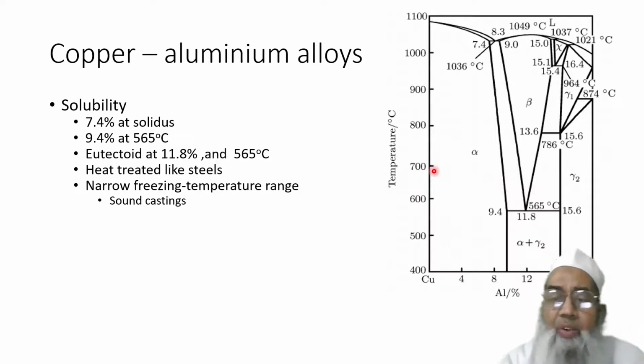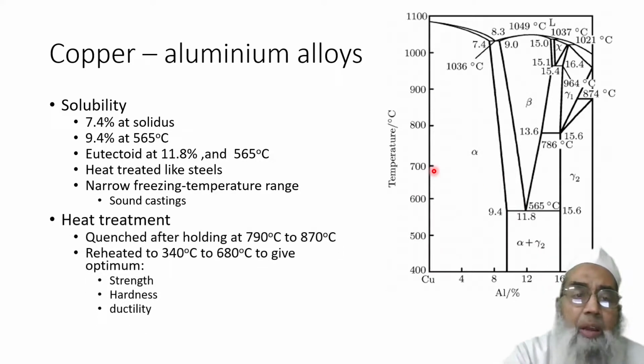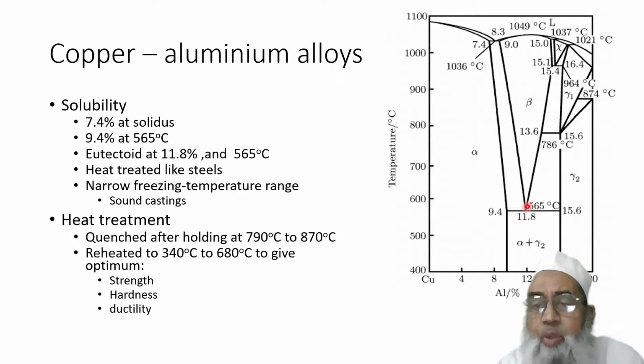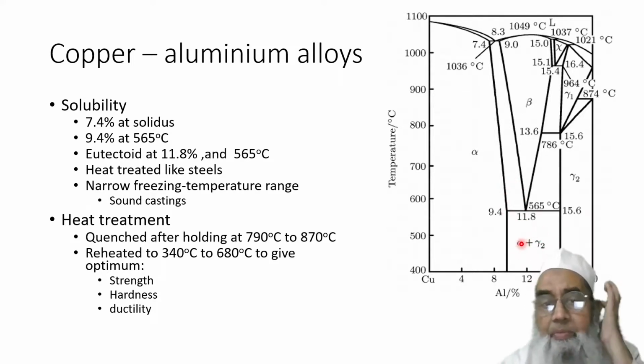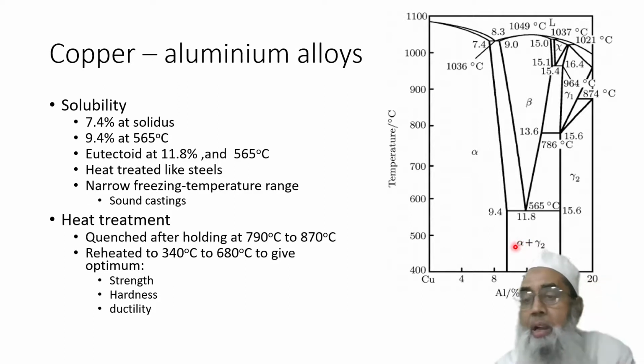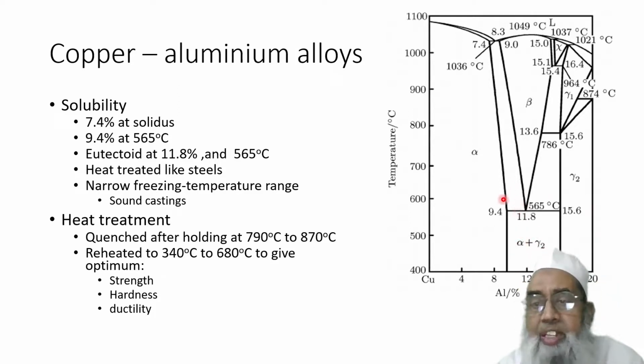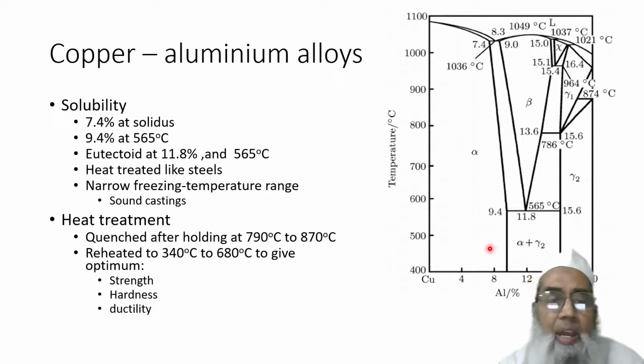we can see that this is the alpha phase, which is soft. But this is the eutectoid, at 11.8% aluminium, and therefore after that, if we cool down, it separates into two different phases, but this gamma phase is hard. Alpha phase is soft, and therefore if we can capture this gamma phase by heat treatment, then of course the hardening can be done, and therefore quenching for heat treatment.